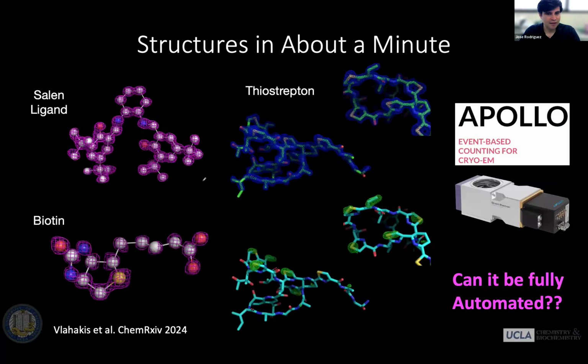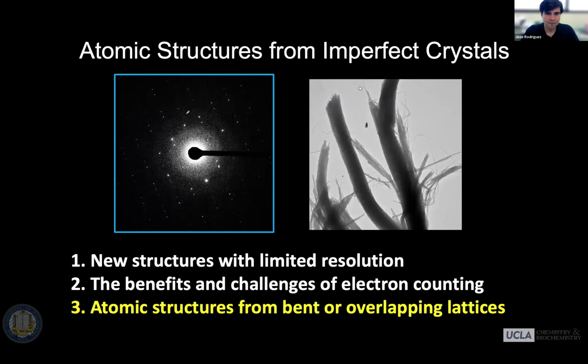And the benefit of doing this is that even though you've used a very low dose, you can get fairly accurate structures. Here I show you a sample of structures of salen ligand, of biotin, and of this thiostrepton peptide. And these are collected on the order of about a minute. And that data, of course, is for a single crystal, but you can merge a few if needed and determine these structures within about a few minutes. None of this at the moment is fully automated, but there is the potential with using these detectors to also use companion software that drives them and the microscope automatically. And so the promise is there to basically make this whole thing fully automated.